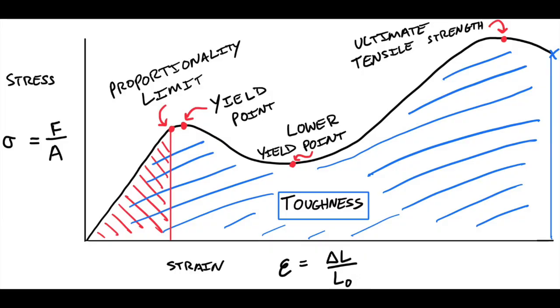At the beginning of the stress-strain curve there's an elastic regime with a linear relationship between stress and strain. Then the material may yield — consider something like a polyethylene plastic bag that stretches a little and returns, but only by about 10%. Then the crystallites yield and you start strain-aligning those chains. There may be a lower yield point where less force is needed to continue stretching. But eventually all those polymer crystallites are disrupted and realign, becoming really strong because all molecular axes are aligned along the stretching direction like ropes — much harder to pull apart — until finally it fractures.